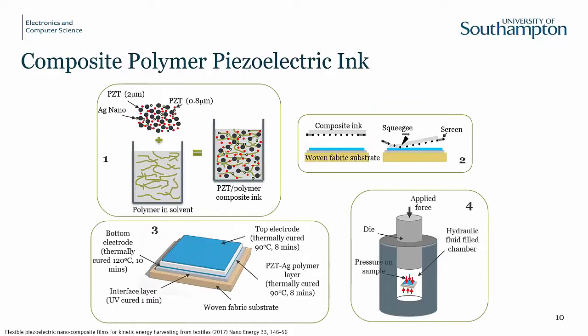So when it comes to piezoelectric, we did look at PVDF as an obvious sort of polymer approach for this. However, the so-called printable forms really aren't very printable. They're horrible to work with. So we developed our own composite ink, where we took a blend of piezoelectric powder of different particle sizes, mixed it with a very small concentration of silver nanoparticles, and mixed this with a suitable polymer into a composite ink. It's very nice to print. We typically print that between two silver electrodes, making a sort of capacitor sandwich structure. And then if you really want to go all the way and make the best possible performing material, you can do this isostatic pressing process, which adds probably about 10% to the performance of the material, but not really practical.